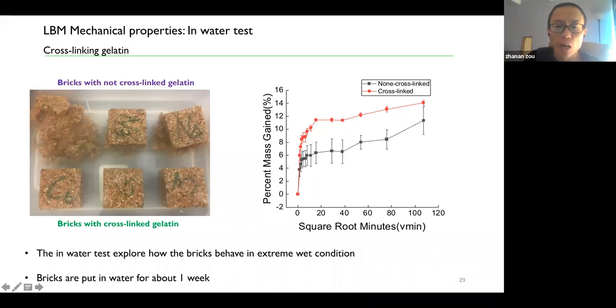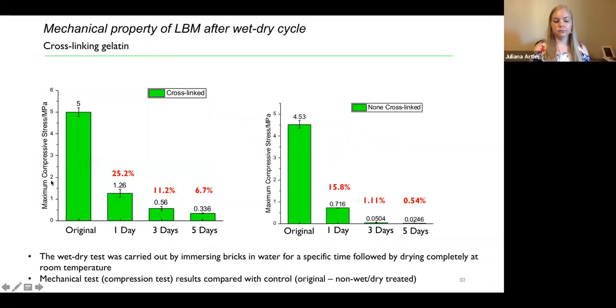So keep this in mind. We carry out another test. If you move to the next page, which is a wet-dry cycle test. So the test is really similar. We still put the bricks in the water for a certain amount of time. Here, as you can see, we put the bricks of both the cross-linked one and the non-cross-linked one in the water for 1 day, 3 days, and 5 days respectively.